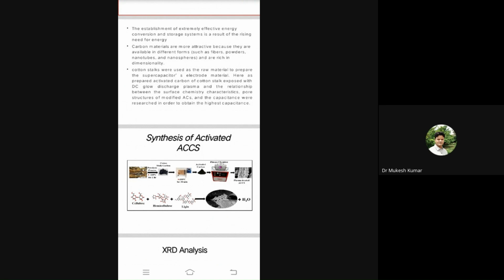in dimensionality. Now, my present work is cotton stalks used as a raw material to prepare the supercapacitor electrode material. Here the prepared activated carbon of cotton stalks is exposed to DC glow discharge plasma, and the relationship between the surface chemistry characteristics, pore structure of modified activated carbons and capacitance were researched in order to obtain the highest capacitance.